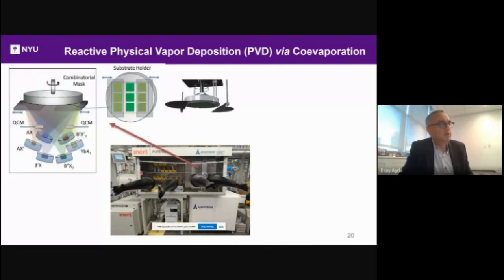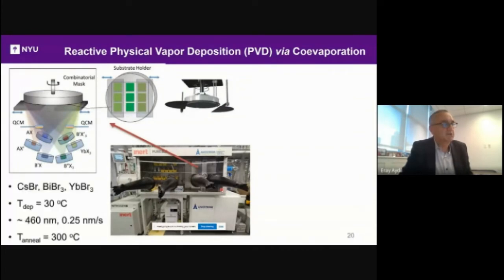We do our synthesis using reactive physical vapor deposition via co-evaporation in a glovebox chamber. We have 6 sources into which we can put various metal halides, and a combinatorial mask that allows us to deposit many materials at once. It's all programmable, so we can go through many different compositions relatively fast. For the rest of the talk, the sources are cesium bromide, bismuth bromide, and ytterbium bromide. Deposition temperature is 30 degrees centigrade. Typical film thickness is about 460 to 500 nanometers, at about 2.5 angstrom per second, and we anneal them at around 300 degrees centigrade.